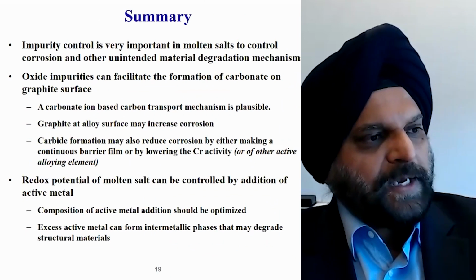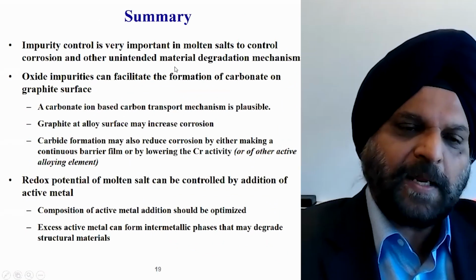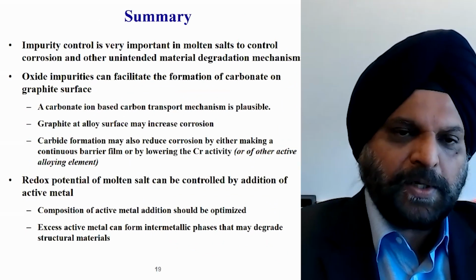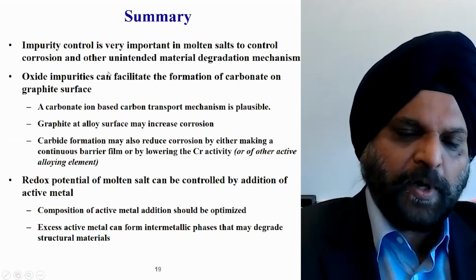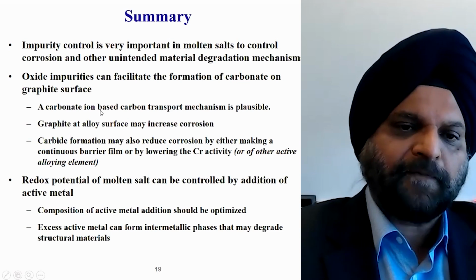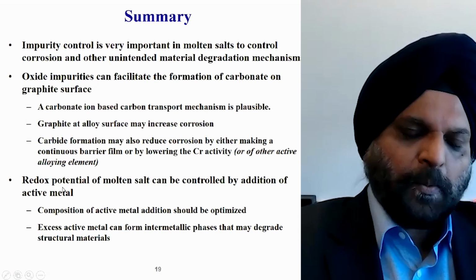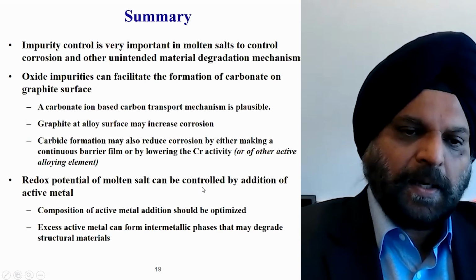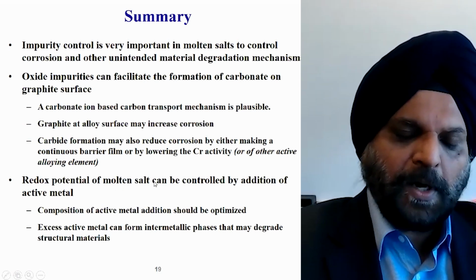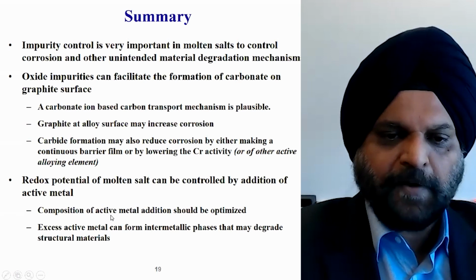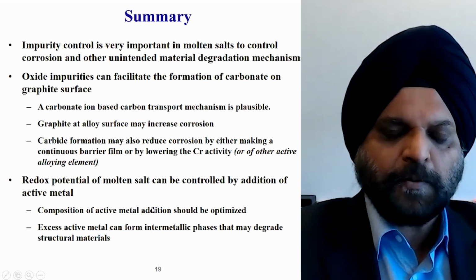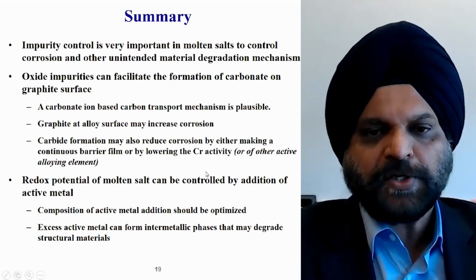So with that, I'm going to stop, but impurities are very important. Oxide impurities do not register as much in fluoride potential, but they can have indirect consequences. When we are using redox potential, depending upon how we use it, if we have active metal addition, we have to be mindful of their reaction with alloying elements. With that, I'm going to stop.